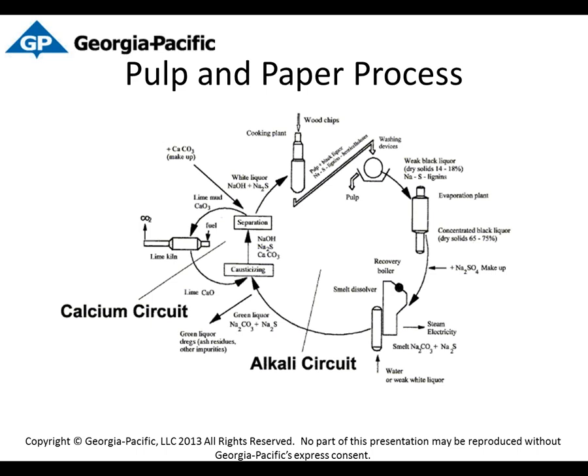So we evaporate the water from the black liquor, send it into a boiler to burn it, and we recover that sodium hydroxide and sodium sulfide chemical and send it down to our causticizing plant where we actually slake the lime inside the liquor solution to get back to sodium hydroxide, because it actually comes out as sodium carbonate. I know that's a really quick process overview, but it's just to give you a general idea of the kind of chemicals we're dealing with and some of the environments we're dealing with.